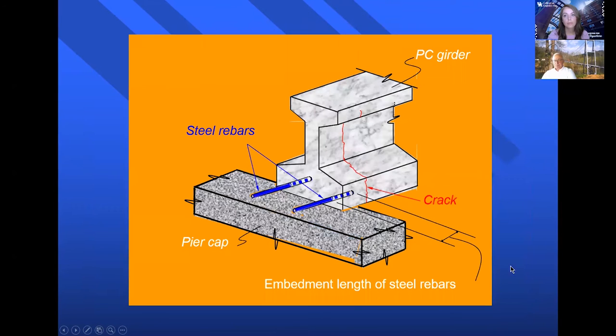And on another portion of I-65, we had these pre-stressed concrete beams that had some cracking right about a foot away from the pier cap. These cracks are generally due to temperature and shrinkage. And we had about 120 locations on beam ends that had these cracks, and some of them were severe. But what really was very confusing to us at first is, why are they all forming about a foot from the pier cap? And there were no plans for this bridge. Finally, one engineer, an old-timer, told us that they used to use these double bars between the two beams at the ends, and that ended about 1 foot into it. So basically all the cracks initiated at the tip of this double bar.